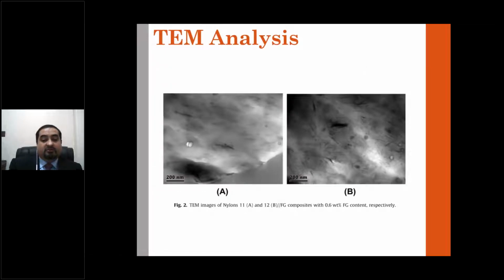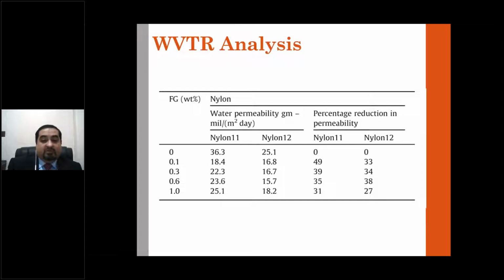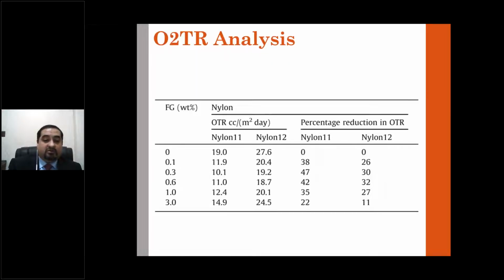Here you can see very good dispersion and distribution of the individual graphene layers that we were able to separate out. You can see a few of the agglomerates. This thing you need to keep in mind: the individual layers will separate out, but a few agglomerates will always remain. So we are always trying to restrict their amount. We cannot eliminate them. The water permeability, once again, for both nylon 11 and nylon 12 showed good properties even at very low weight percentages of both materials. The same was true for oxygen transmission rate analysis.